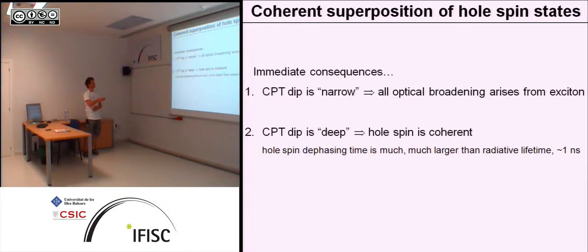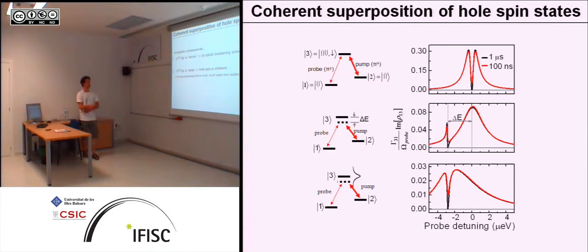The dip is very narrow, while the optical transition is broad. That means that the coupling mechanism broadening the electron in the excited state doesn't affect the hole spin of the ground state. The other thing is that it's deep, so it must be very coherent, much more coherent than the radiative lifetime of 1 nanosecond of this transition.